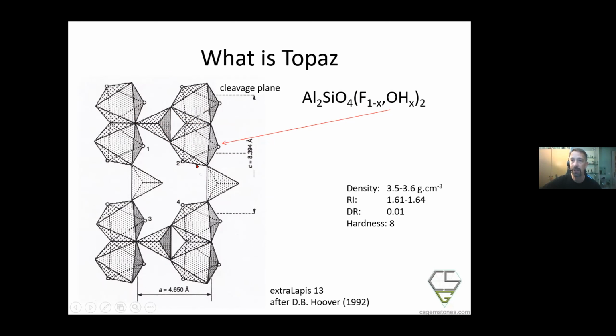And what we have here and what is very typical for topaz is 90 degrees to the C-axis, we have a perfect cleavage plane. So this is one of the problems with topaz. It is very hard. You see here we have a hardness from the Mohs scale of 8. But the problem is if you ding it in the right direction, it will break along the cleavage plane. And therefore, also, if you look at the mineral specimens that are available, you will have many, many single crystals, but only rarely you have matrix pieces because they just break off the matrix easily.